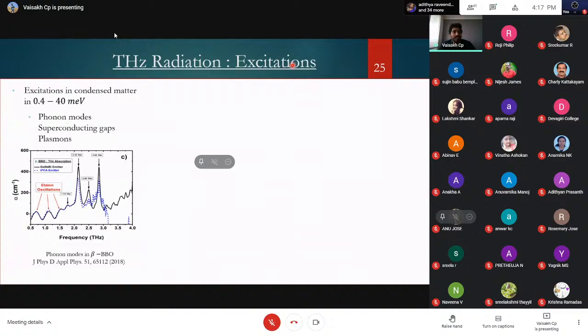First of all, a lot of excitations in condensed matter systems happen to be in the terahertz range. Many phonon modes. We know that the infrared spectrum corresponds to intramolecular vibrations, but terahertz is not as strong; it drives intermolecular vibrations, like phonon modes. Superconducting energy gaps have terahertz energies, and so do plasmons. Here we see the phonon modes in beta barium borate crystal, which are these peaks, the specific frequencies that are absorbed in the material.